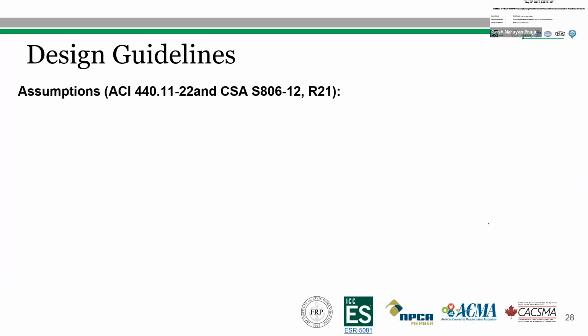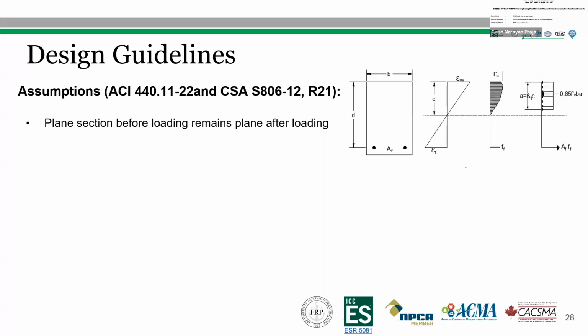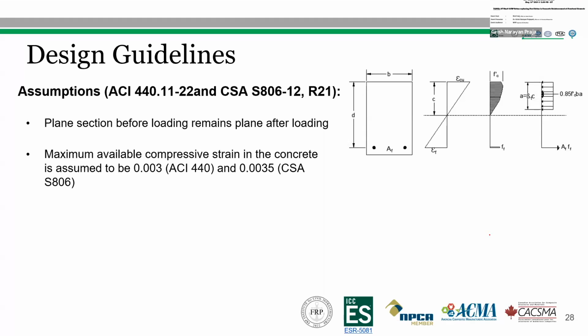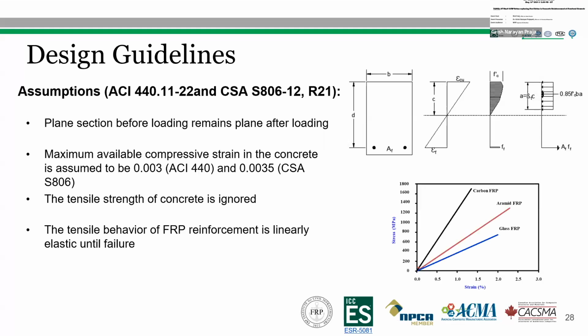The assumptions made in the design of FRP reinforced concrete structures, according to both CSA S806 and ACI 440, are the plane section assumption: a plane section before loading remains plane after loading, which means that the strain developed in concrete is proportional to the strain developed in the FRP bar. The assumed maximum allowable concrete compressive strain is 3000 microstrain according to ACI and 3500 microstrain according to CSA S806. The rupture strength of the concrete is very low and should be ignored in the design. The tensile behavior of the FRP reinforcement is considered linearly elastic until failure, and a perfect bond exists between concrete and FRP bar.